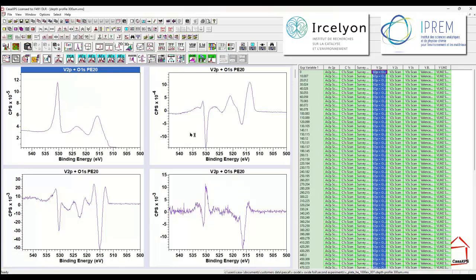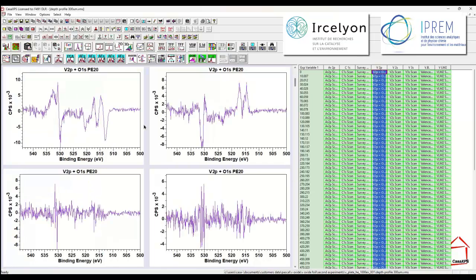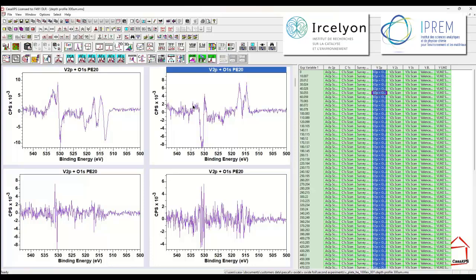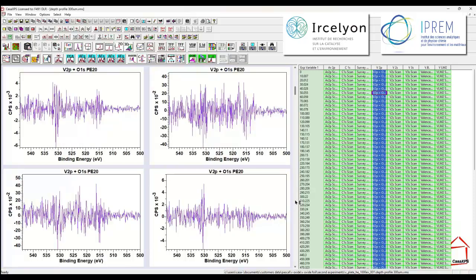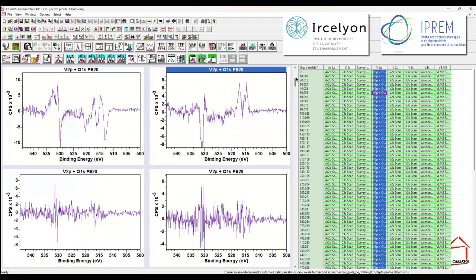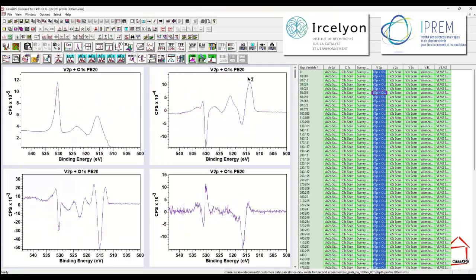For each of these abstract factors that have signal, they must be included in that calculation. So here we have five and six abstract factors that look like we need to include six abstract factors to reproduce the data within the type of error that we would expect for Poisson statistics, and that's because the seventh abstract factor looks very much like noise, and so does the eighth and all subsequent abstract factors. These are all looking like noise.